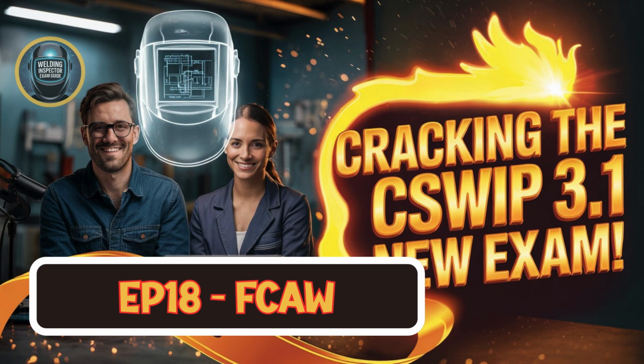But there's always a but. Yeah, the but is significant. It's much more sensitive to moisture getting in through that overlapped seam. If it gets damp, it's basically ruined. You also can't copper coat it easily, and the sheath tends to be thinner, which might require more careful feeder setup. So the way it's made directly impacts things like moisture resistance.